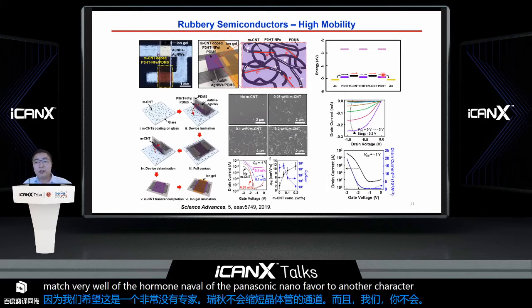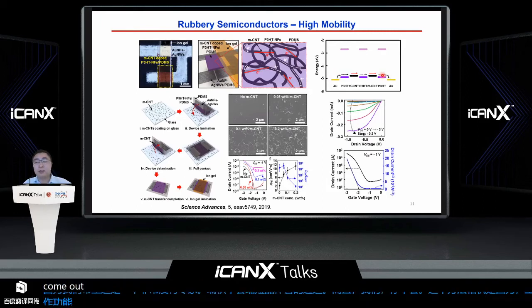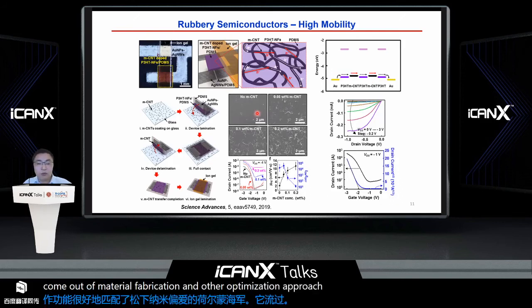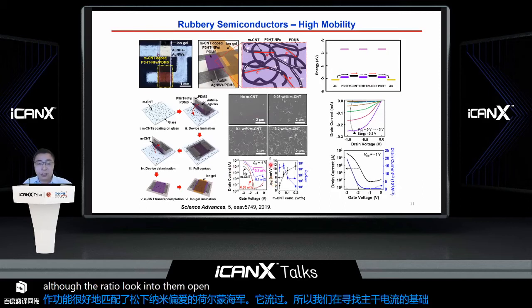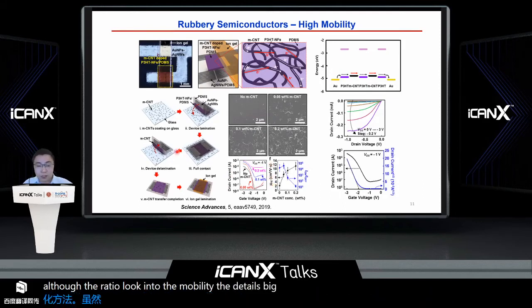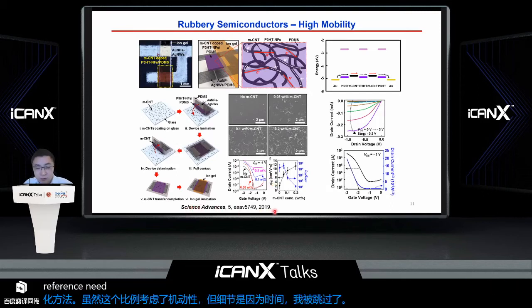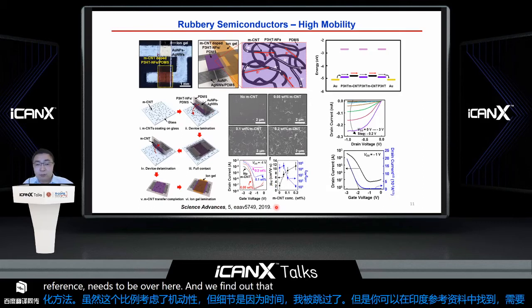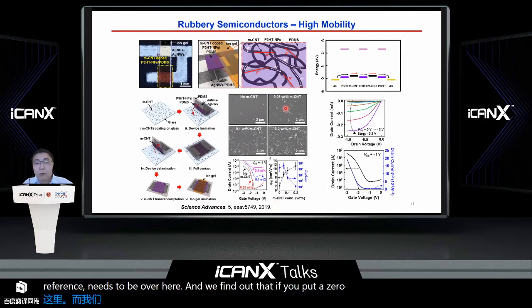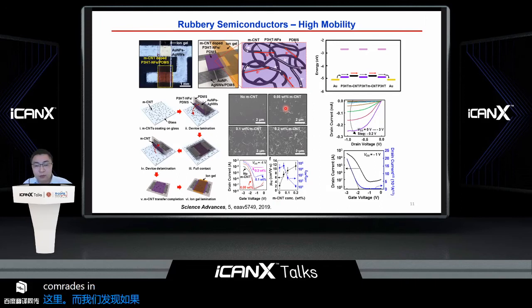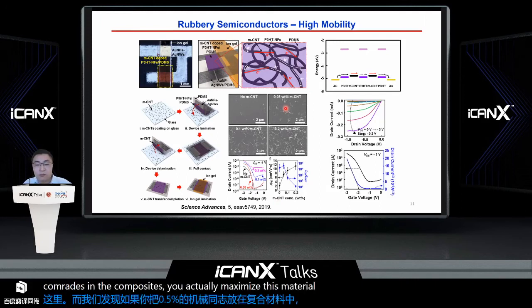We came up with a material fabrication and optimization approach based on looking into the drain current, the on/off ratio, and the mobility. The details I will skip because of time, but you can find them in the references listed below. We find that if you put 0.5 weight percent of metallic carbon nanotube in the composites, you maximize this material with fairly high mobility and also a high on/off ratio.